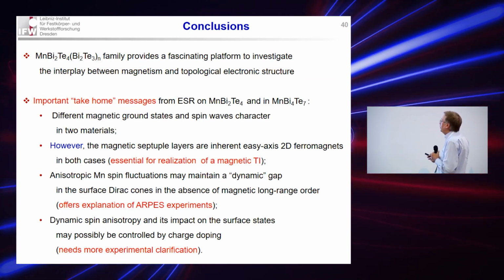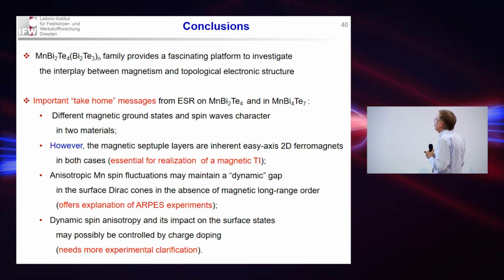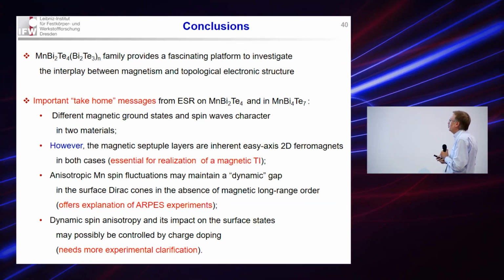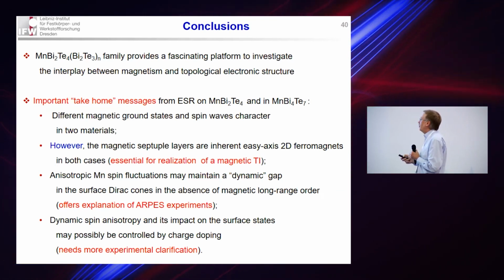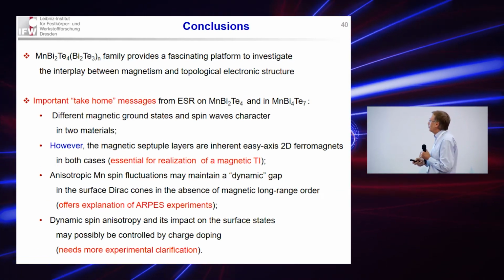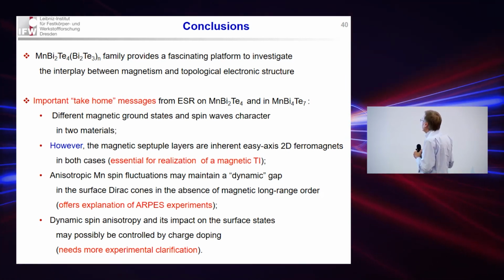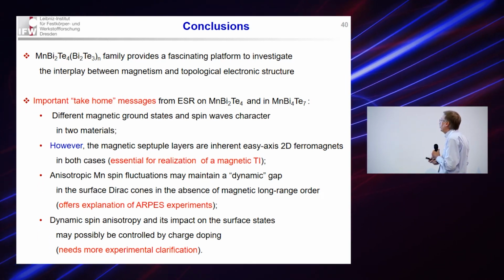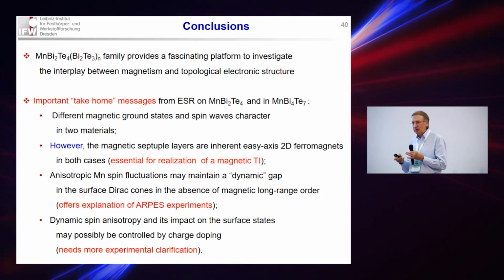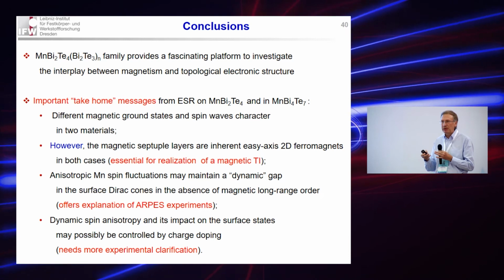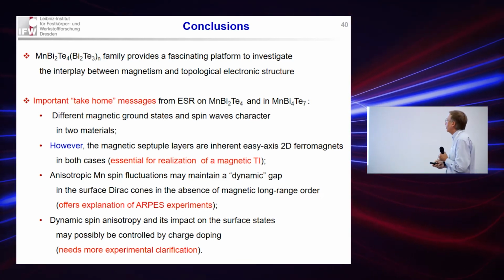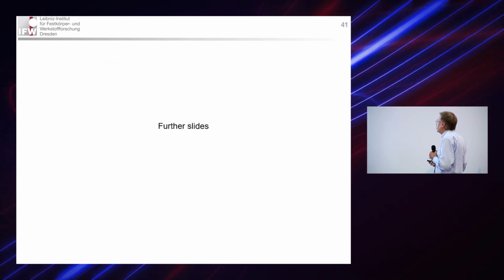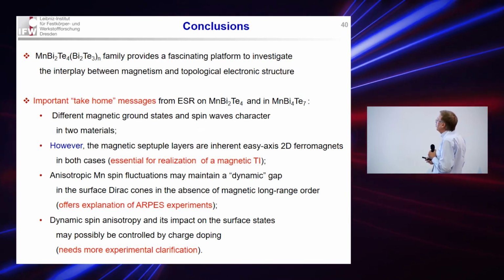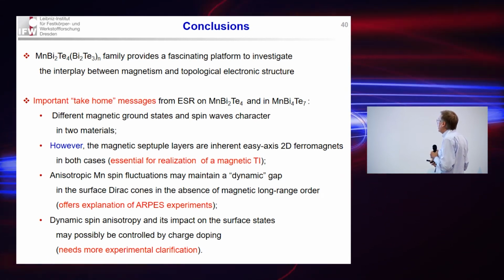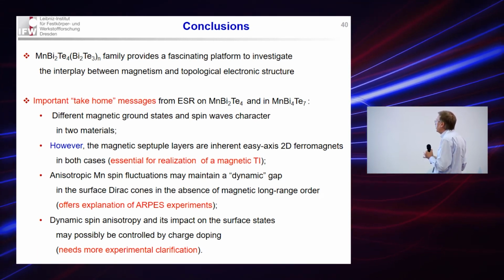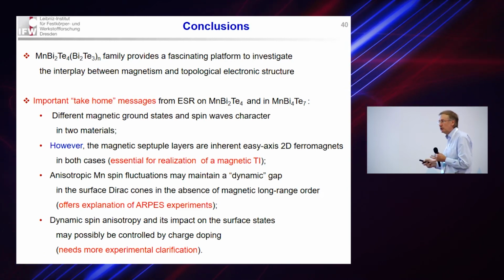In my talk, I gave you a flavor of this new manganese bismuth telluride family of magnetic topological insulators, which provides a fascinating platform to investigate the interaction between two apparently conflicting states of ordered matter, the magnetic order and the electronic order. And what we could learn so far from our electron spin resonance experiment is that indeed in the magnetic ground state, the spin waves are very different in these two materials.